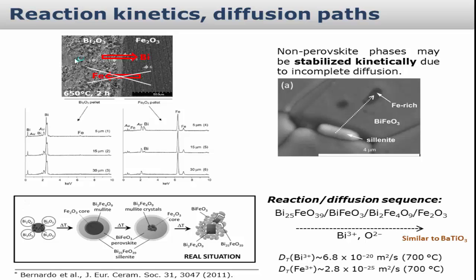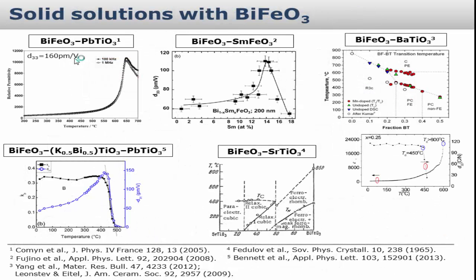And this might not happen at a certain temperature, because the diffusion path becomes too long. It will not happen, and you will have an image like here, where you have this sillenite phase at the grain boundary and this iron-rich core, which is stabilized kinetically. It's just that the reaction stops at a certain stage. So this is another view of how a secondary phase may be present in the final ceramics. This case of BiFeO3 is pretty simple. It's still tough to prepare phase-pure BiFeO3, but it's relatively easy to understand.